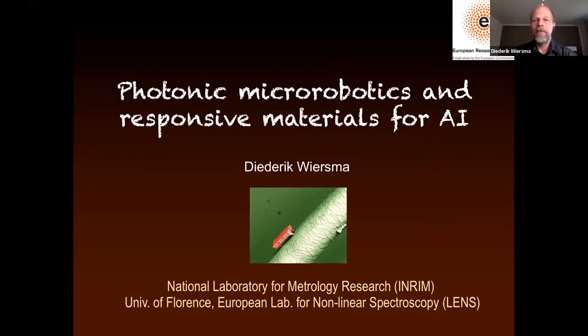Having said that, optical tweezers in this case, we don't think are a good idea, but there are two effects playing a role in the polymer. One is the direct absorption of a photon, which will change the configuration of the molecule from trans to cis. So that is one effect. The other effect is that the photon is first absorbed. It locally generates a little bit of heat, and this heat is now used in making a mechanical action. And there are certain advantages and disadvantages. So both strategies are okay. The first one is a little bit slower. The second one is a little bit faster.